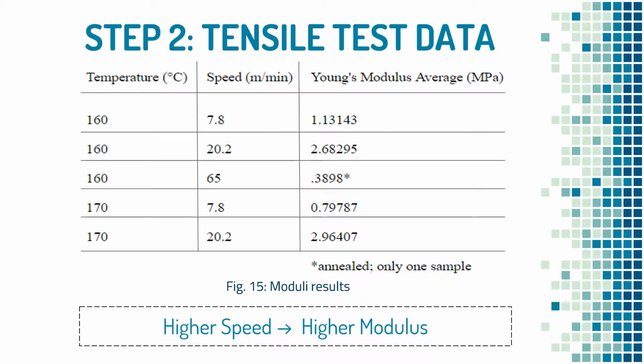For us, it was 12 hours. This resulted in when we placed the initial load on the fiber, it snapped almost immediately, giving it a Young's modulus much less than the rest. Now, even though that fiber was extruded at a speed way beyond the rest of the other fibers, the effect of speed on the Young's moduli was completely canceled out by the annealing process.